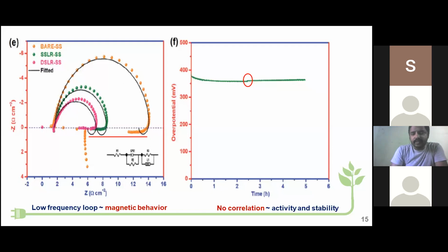Why does it attain a steady state? This zigzag motion is happening because of the polarization. That is, the surface oxides undergo polarization up to 2.5 hours. After that, the polarization is stopped, so it reaches the steady state. From this, we concluded that there is no correlation between the activity and stability of the electrocatalyst.